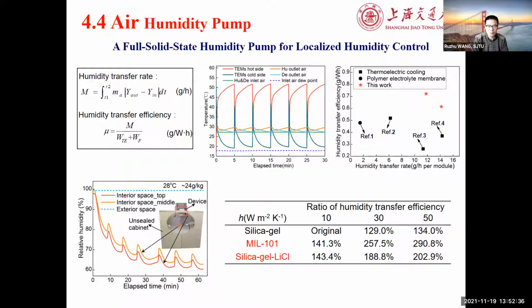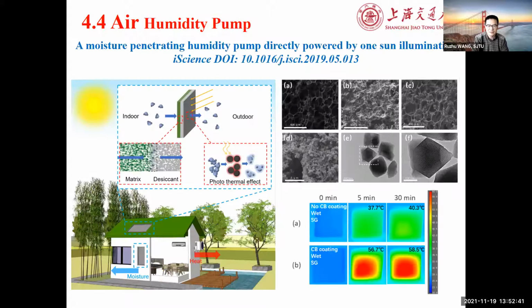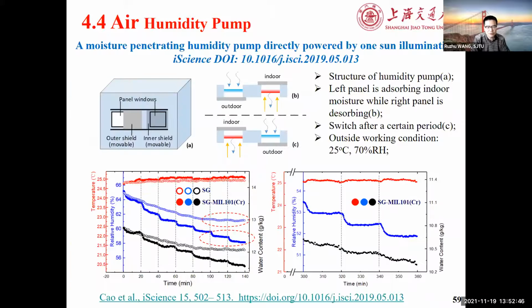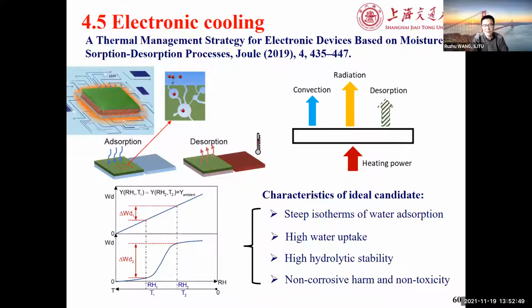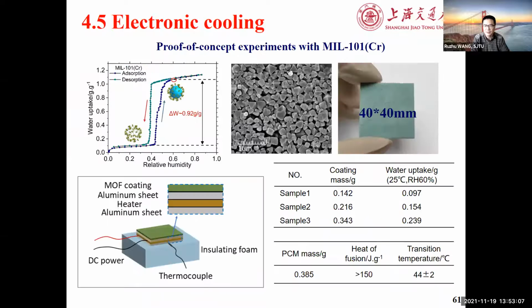We also did more on applications in buildings for humidification with solar, and did a test. And very recently, one paper in Joule on thermal management for electronic cooling. With sorption, when there is high temperature under heavy load, the temperature goes up, but it will get the regeneration of moisture, so it will restrict the temperature rise. This is a test where we used less than 1 gram of material.